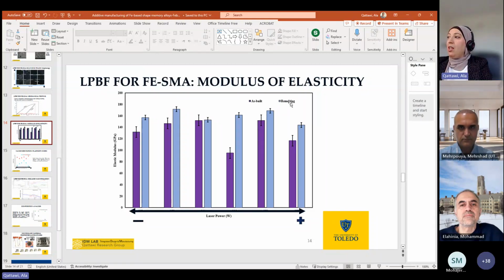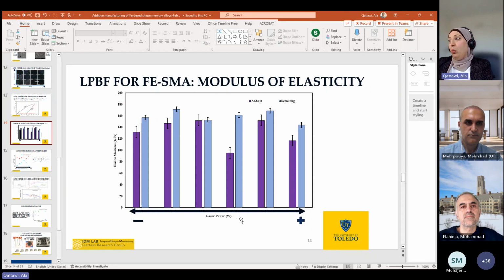So the remelting is a slower pace with a slower power laser that passes through the layer and basically improves the mechanical properties. Why this happens at each different laser power and laser speed is because of the differences in the thermal signature on the melting pool. So that needs more understanding of the melting pool itself, melting pool analysis.